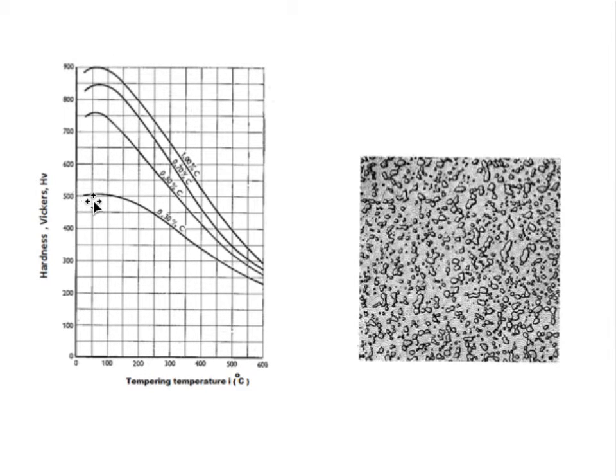So we can see here the starting hardness in the martensite that it increases strongly with carbon content. So here we have a very, very hard martensite. If the carbon contents are low, below 0.2, the martensite is not so very hard. It actually can be acceptable and used. But anyway, if you have these type of steels, they need to be tempered. And then we see what happens if you temper it at different temperatures. We see that the hardness goes down rather strongly for the high carbon content alloys. In half an hour at 600 degrees, and we are down here at 300 Vickers.